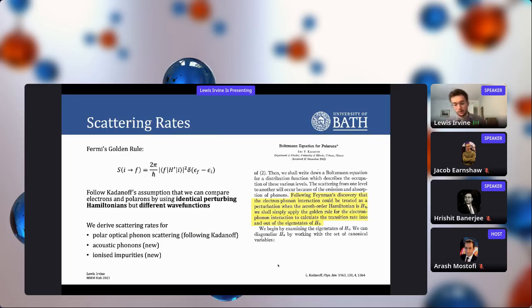Okay, we want to work out polaron transport properties. So then we need scattering rates. Kadanoff did some great work back in the 60s with his Boltzmann equation for polarons. And we're going to use the framework that he used, which was that we can compare electrons and polarons directly by using identical perturbing Hamiltonians for the scattering rates, so interactions with phonons or impurities. But we use the different eigenfunctions for the free band electron and the large polaron. Using that, we can compare them directly and see what differences polaron theory makes. So we derived scattering rates for polar optical phonon scattering as Kadanoff did. But then we also derived scattering rates for acoustic phonons and ionized impurities, which have been claimed to be important in halide perovskites in various bits of the literature.